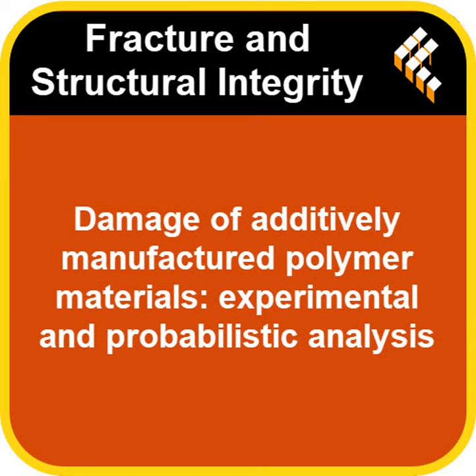And stage 3, the final act. Stage 3 is the abrupt propagation stage. This is the critical phase. Damage accelerates rapidly, becomes uncontrollable, leading to sudden, catastrophic failure. And this stage consistently began when the crack reached, what was the number? Roughly 50% of the specimen's width, a life fraction of about 0.5. So that 0.5 life fraction is a really key threshold, it seems. It really appears so based on their experiments.